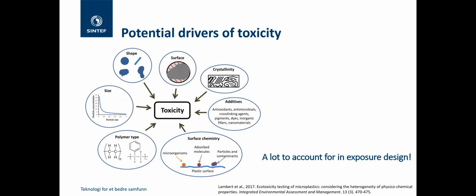When we think back to the complexity of microplastic as a pollutant, there are a large number of potential drivers for the observed toxicological responses. That includes polymer type, the size of the particle, the shape, surface characteristics. I think there's been 1 or 2 studies on the crystallinity of the polymer. There's all of these additives and other chemicals associated with plastic that could be a potential driver, and then surface chemistry and surface characteristics, shall we say. So the particles and contaminants on the surface, any adsorbed molecules, changes in the surface chemistry due to degradation, and potentially the presence of microorganisms that colonize the surface.